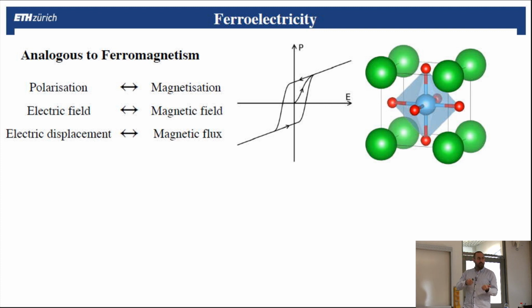So I presented magnetism. Let me go to ferroelectricity. It is actually very similar, or analogous, to ferromagnetism, because you can replace magnetization by polarization, the magnetic field that you apply by an electric field, and the magnetic flux by the electric displacement. And you also find this type of hysteresis, where when you apply an electric field, you produce polarization in your material, and when you remove the field, you don't go to zero. And you can apply the opposite field and switch to the opposite direction.